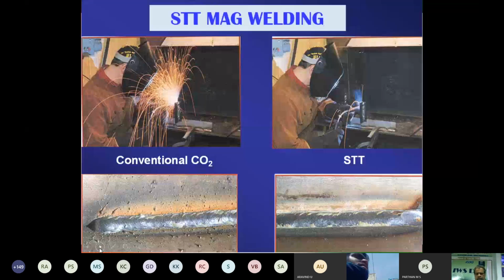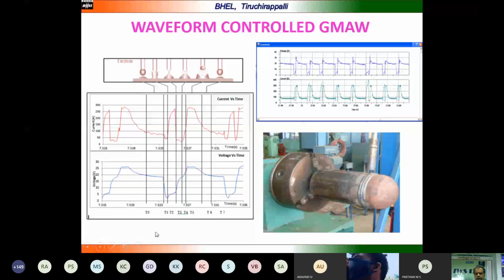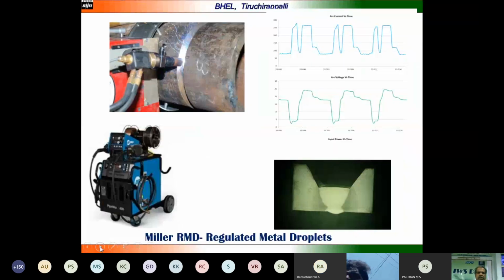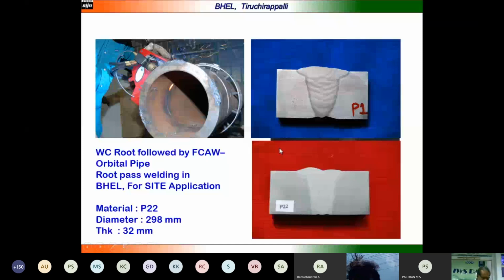This waveform control process has been successfully developed and applied for welding of such pipes and receptacles using the STT process. The root pass is done, and the subsequent passes are done by the conventional GMAW process. Orbital pipe welding by the GMAW process can use these short circuit or modified waveform processes using power sources, and the welding can be done very easily for pipe welding. Orbital pipe welding can use these processes. The waveform control root pass followed by FCAW can be used for orbital pipe welding, and the weld quality and everything can be achieved very easily, and it can meet the requirements.